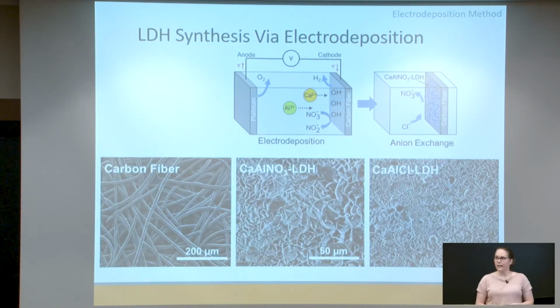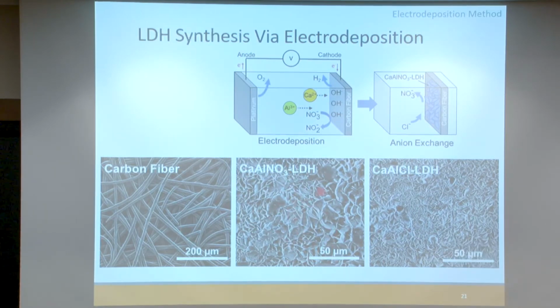So if we have a look at some electron microscope images of what things look like at the various stages of deposition, what we see here is that this is the starting carbon fiber. After the deposition has occurred, we end up with these flat plate-like sheets that are indicative of layered double hydroxide, and after the anion exchange, we end up with slightly different morphology, but we still have those plate-like sheets that are indicative of the layered double hydroxide.